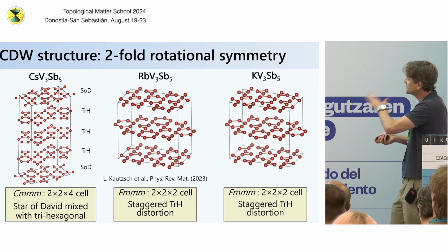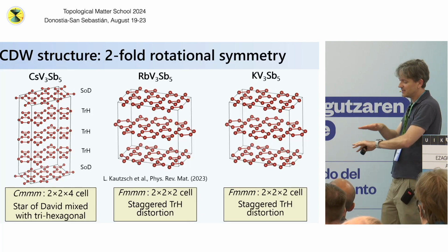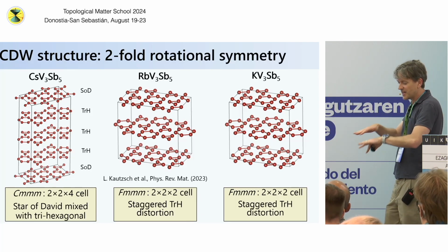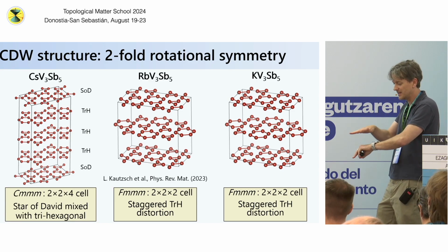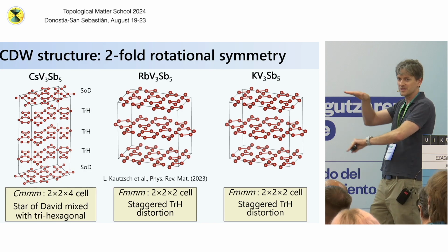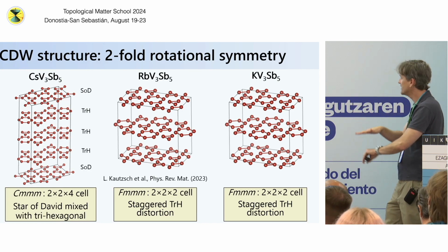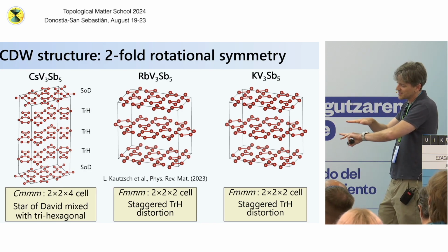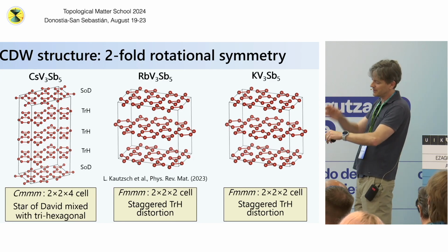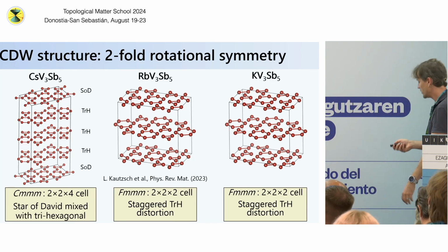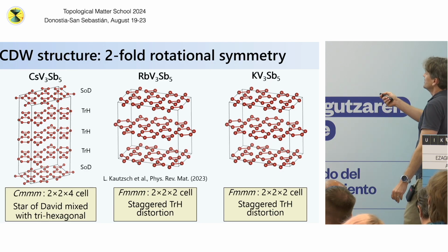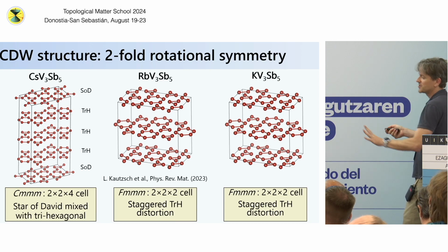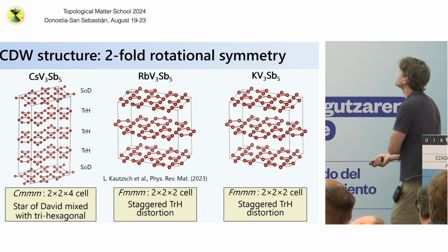And so the distortions that are in general energetically favored in these systems are for each Kagome plane to breathe into one distortion type or the other, and then the differences are in how they stack along the c-axis. So it's a three-dimensional charge density wave phase, but they can phase-slide half a unit cell relative to each other along the c-axis, or they can, for instance, modulate the distortion type along the c-axis. These are some details, but indeed they all form three-dimensional charge density wave states. Okay.